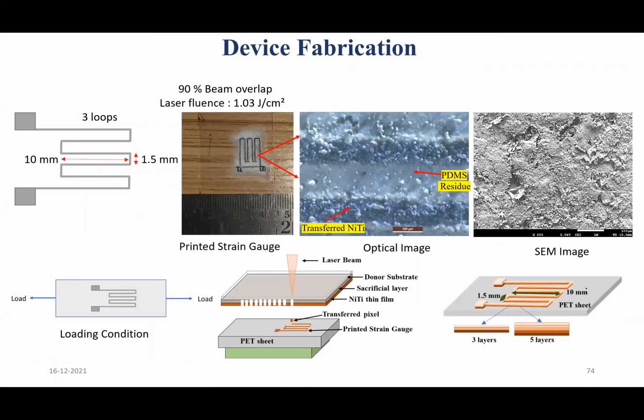There is a donor substrate and a sacrificial layer, and we have deposited our NiTi thin film using sputtering, and then the transfer happens. We wanted to compare with the commercially available strain gauges, which are available in different widths. With a single shot, we can build up to 300 nanometers. So we have gone for 3-layer and 5-layer, and we have checked the performance.